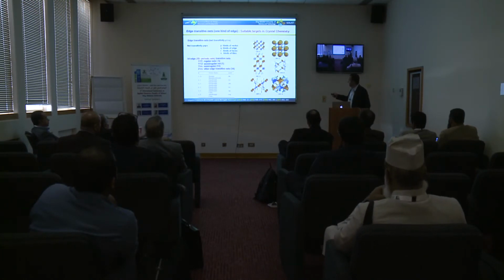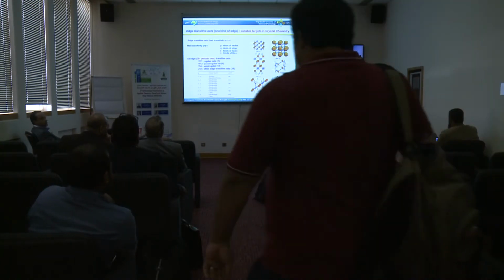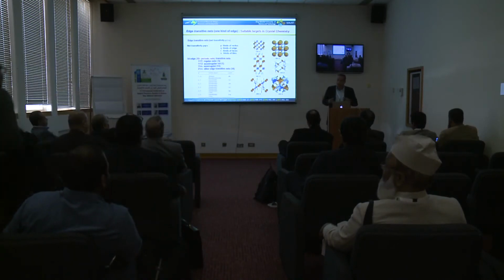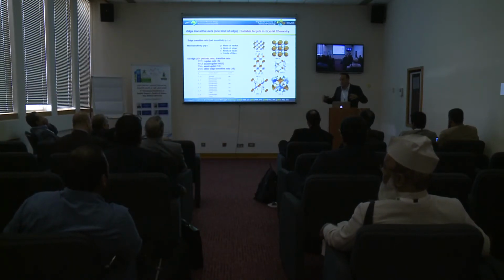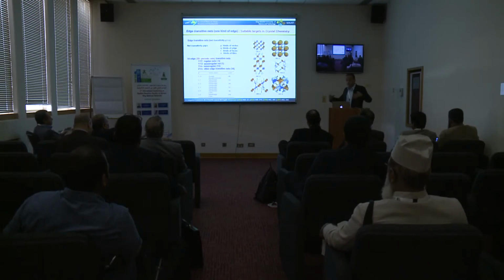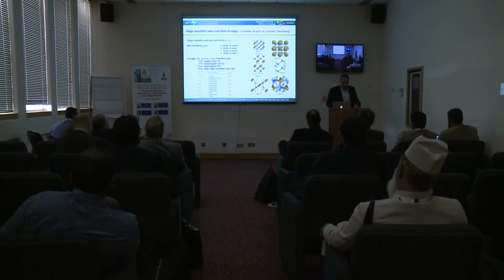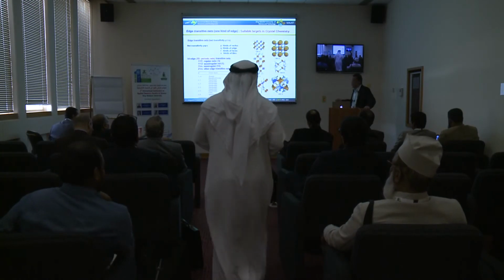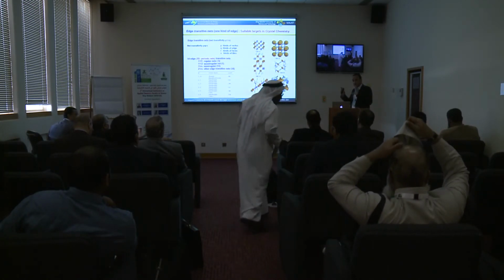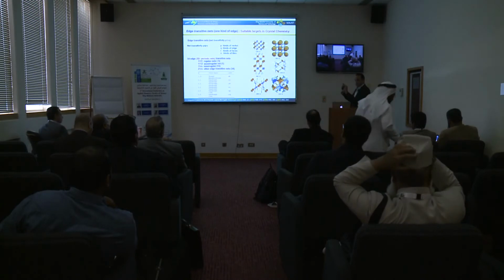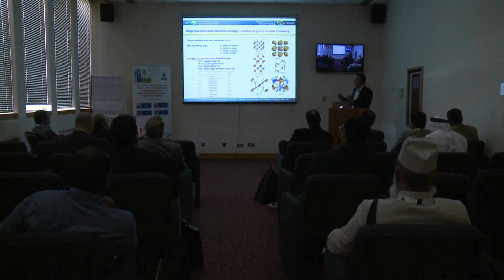I will not get a chance to talk about this structure here. But for example, if you have truncated cuboctahedron linked with a triangle, there is only one possibility. There is no other. This is called rht. And this allows you to extend those structures to the limit of crystallography. This material was actually used by the Northwestern group, where it holds the record when it comes to surface area, where they extended the organic link to that extent. So this is the blueprint, meaning that if you have a blueprint to target, you can actually use this.